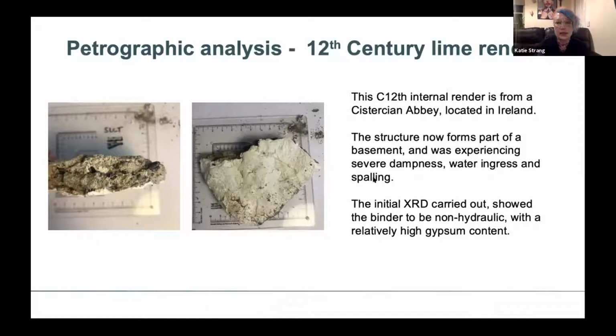Basically the client got in touch because they wanted to know exactly why this was happening, but they also thought that there might actually be some modern paint that had been applied to the surface. What we did when we got the sample in the lab, the first thing to do is a visual assessment. After that, I normally get XRD carried out. That's X-ray diffraction, which will tell you the mineralogy of the sample. That's very important if you want to deduce whether the lime is a hydraulic lime or a non-hydraulic